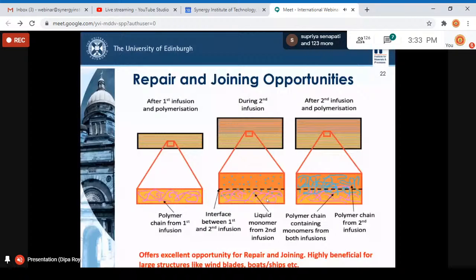So what's happening? In the first go, the resin is polymerized and we get a polymerized laminate. This is the first step of the infusion. Now when we reinfuse in the second step, the liquid monomer is infused into the first laminate. This liquid resin is acting as a reactive solvent. Because of this resin, at the interface or joining plane, the matrix is partly dissolved by the infused liquid resin. This is an advantage of the amorphous matrix, because an amorphous matrix is highly susceptible to attack by solvent. It dissolves the polymer near the interface, and then it polymerizes in situ. So we get a semi-interpenetrating polymer network at the interface.